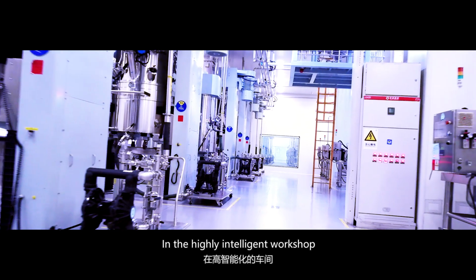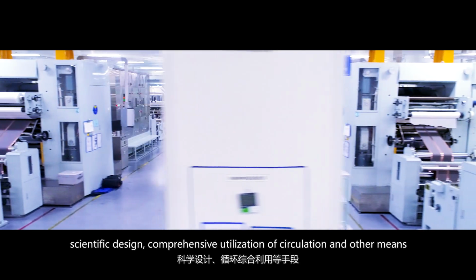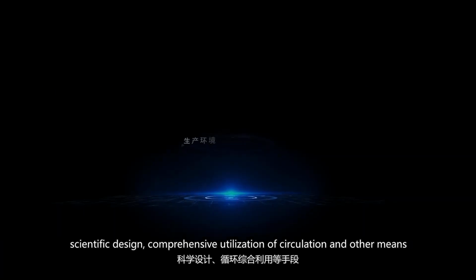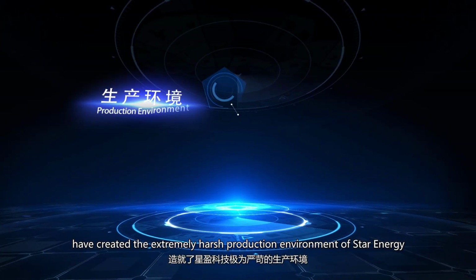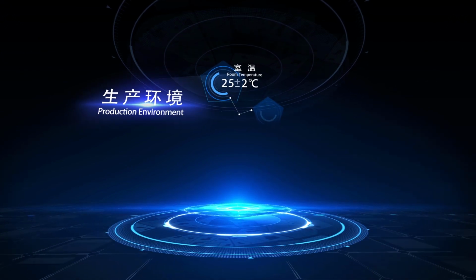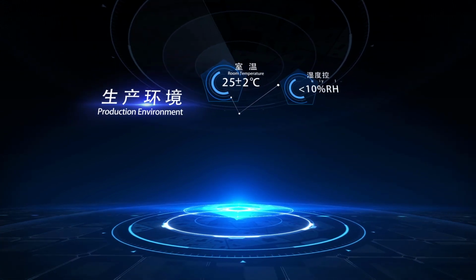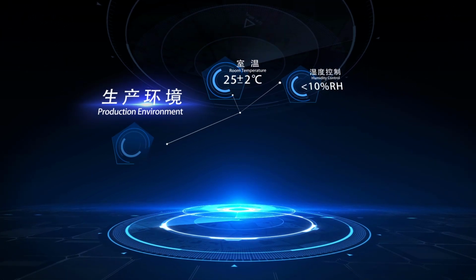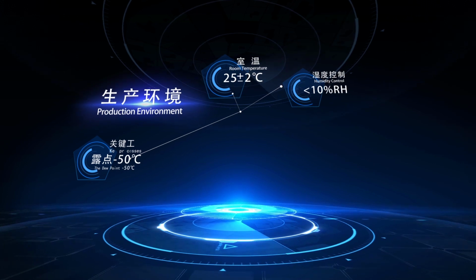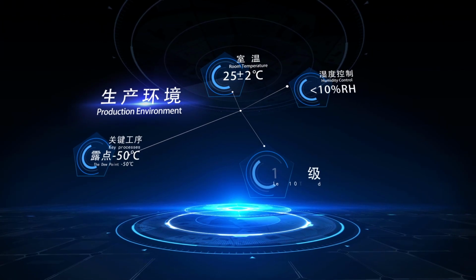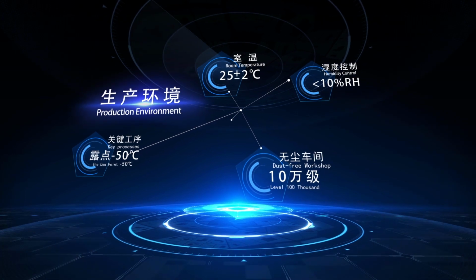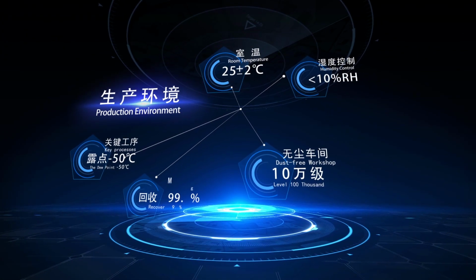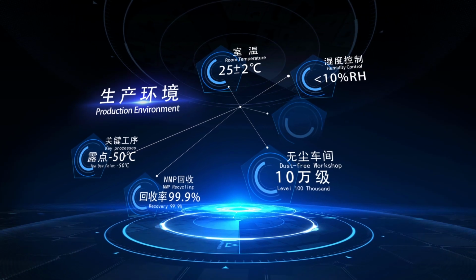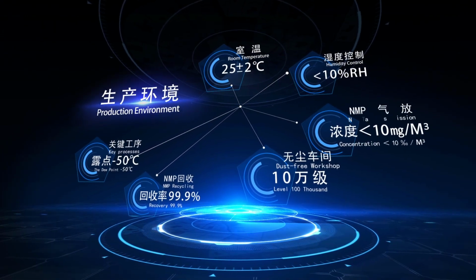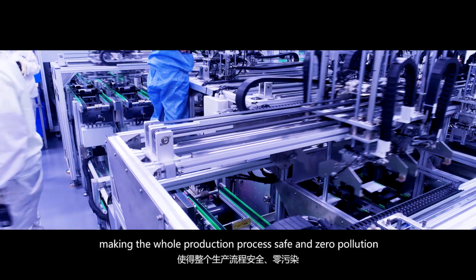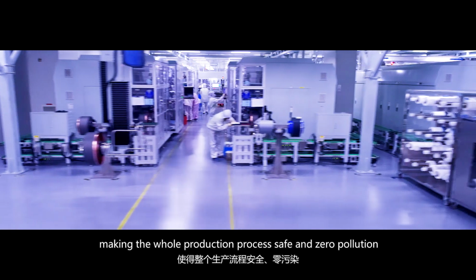The solvent reaches a molecular level of fusion. In the highly intelligent workshop, scientific design, comprehensive utilization of circulation, and other means have created the extremely harsh production environment of Star Energy. Room temperature 25 degrees Celsius plus or minus 2 degrees Celsius. Humidity control less than 10% RH. Key process dew point minus 50 degrees Celsius. 100,000 class clean room. The recovery rate of NMP is 99.9%, and the NMP emission concentration is lower than 10 mg per cubic meter, making the whole production process safe and zero pollution.